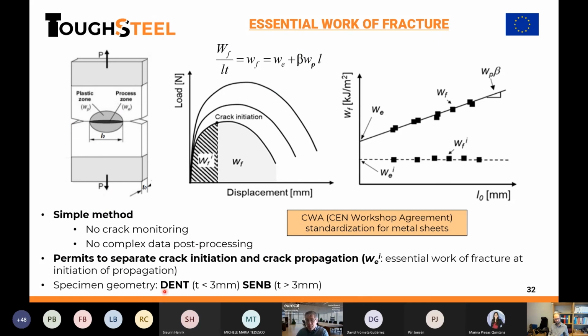But you are right. We mostly applied it to body-in-white parts because it was the huge market for crash. Less than 3 millimeters was perfectly nice. For thicker sheets, these DENT specimens are quite difficult to propagate the cracks in, and also quite difficult to load in tension because the loads are high. And then we suggest single edge notch beam for thicker than 3. And it works very well.